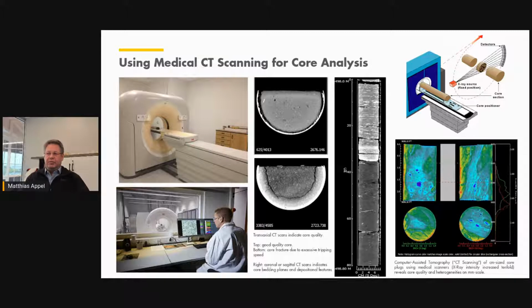So this would be a bad example, by the way. You see quite a heterogeneity in what we call the Hounsfield units, so the attenuation of the X-rays. You see the brighter colors are basically stronger attenuation. You see a bit of invasion on the outside. It is not too much to worry about. You could clean it out, but you see wax inside. You see quite a heterogeneous density profile, pseudo-density profile, which means if you would make core flow measurements with that plug, most of the pore flow would go through that channel here on the inside and not all the other elements of that core plug. You would get a biased answer, biased towards the properties of that more permeable section.